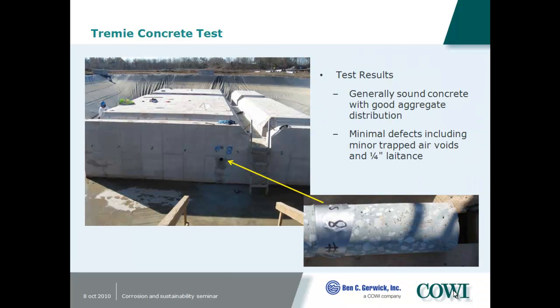They took cores through the shell and through the concrete, and there was a good adhesion between the shell and the reinforced Tremie concrete. So you can see after they removed all of the forms that matched the beams, all the concrete in here was perfectly matching the surface of the underside of the shell, with very little bleeding in this case.